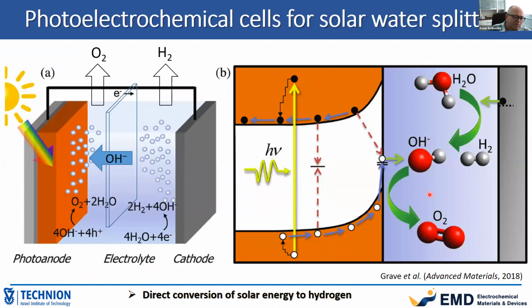So we come with an alternative approach to this problem that dates back to about 5 or 6 years ago, when I was working on photoelectrochemical water splitting, which is essentially combining electrolysis with the photovoltaic phenomenon, where you replace one of the electrodes. Instead of having a metallic electrode, you replace it with a semiconductor electrode, and you take advantage of the photovoltage created in the semiconductor by absorbing light and creating electron hole pairs.